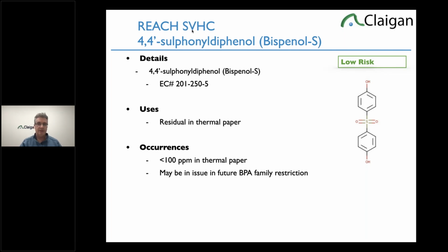4,4-sulfonyl diphenol, bisphenol S. It is really common, extremely common. We test for it all the time. One of the reasons we test for it all the time is that in our lab, we use different thermal papers to seal our bags, and anything that potentially touches our samples, we have to test. And thermal paper has commonly low concentrations of bisphenol S, which in general is allowed for our applications.